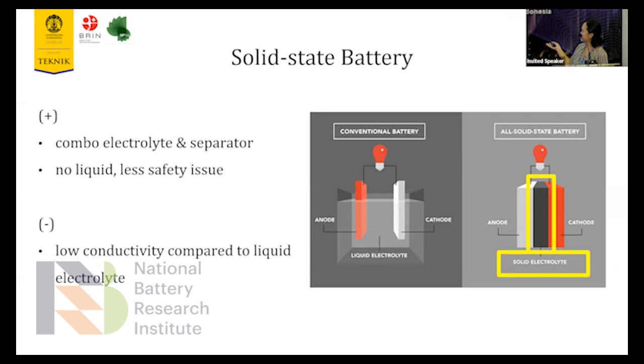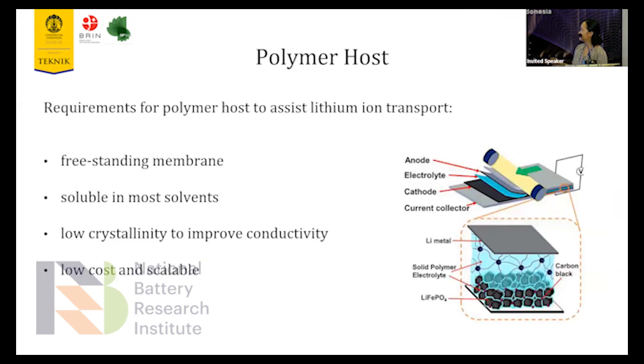On the right side of the picture, we can see that we have no more liquid electrolyte. So we replace them with the membrane solid electrolyte. But it still has a relatively low conductivity compared to the conventional liquid electrolyte.